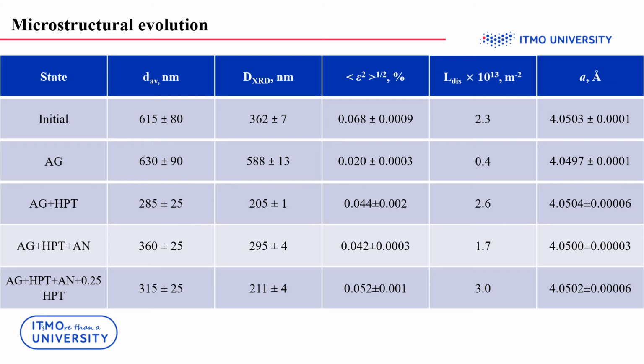However, it is known from the literature that some UFG aluminum alloys exhibit increased plasticity and even superplasticity in some cases due to the significant contribution of grain boundary sliding, or just GBS, to the total plastic deformation. Such intensification of GBS is usually associated with a rather large value of the coefficient of strain rate sensitivity. In this regard, the influence of the strain rate on the observed effect of plasticization was investigated.